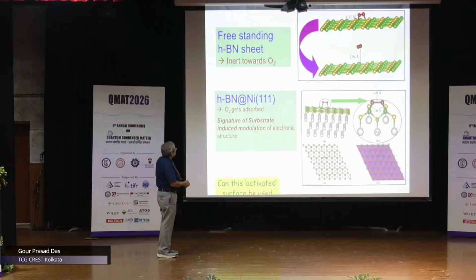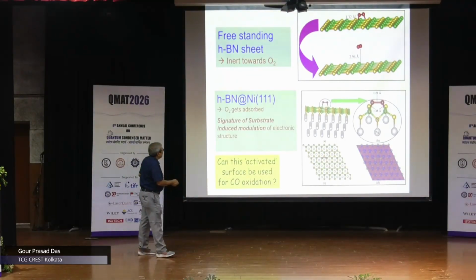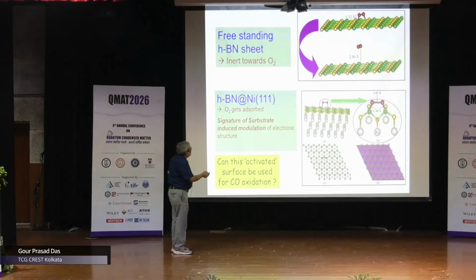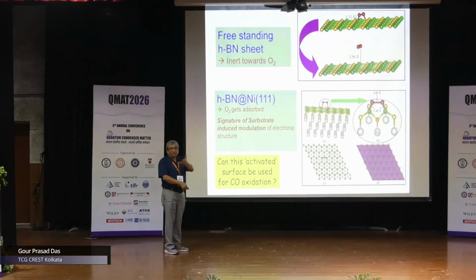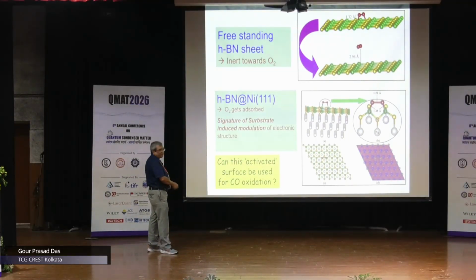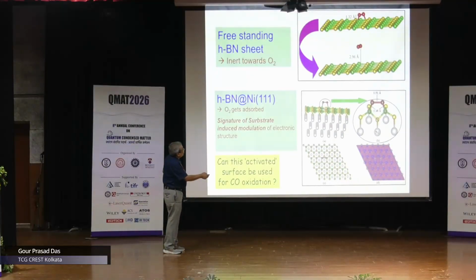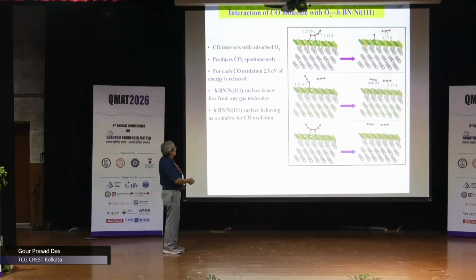Not only does the oxygen stay, but the oxygen distance gets a little bit elongated. The normal oxygen distance, whatever it is from your literature, if you look at it, this oxygen distance is 1.51. It is slightly more elongated than the oxygen distance in O2. Okay? That is what the chemists call an activated surface. And this oxygen distance elongation is something which helps, see the next slide.